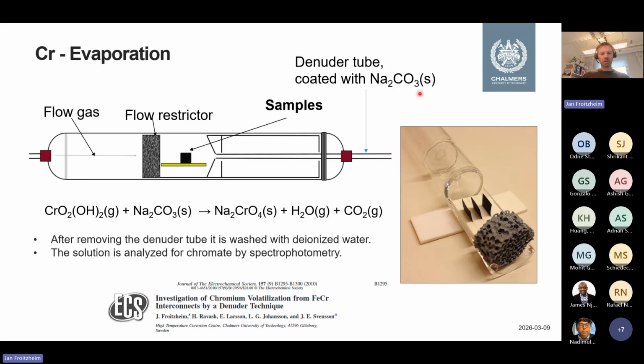And the trick with the sodium carbonate is that the chromium oxyhydroxide reacts with the sodium carbonate and forms sodium chromate. That is deposited in the tube, and then we can just basically remove the tube without touching the samples, replace it with a new one, and then we leach that tube with water, and then we get the chromate solution in water because this is water soluble, and then we can, with spectrophotometry, measure the chromate content in the solution. Pretty straightforward.